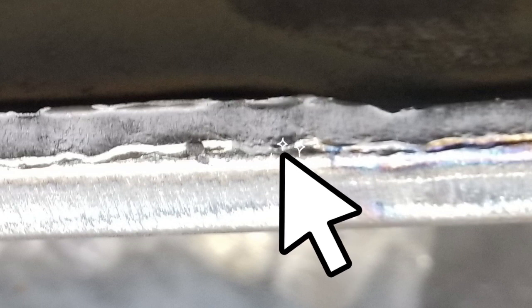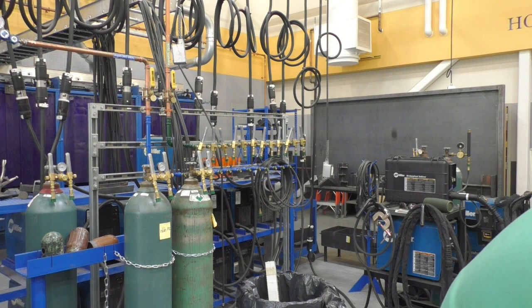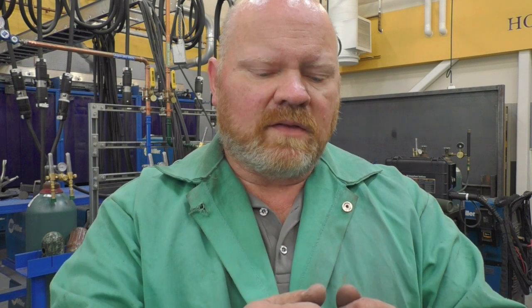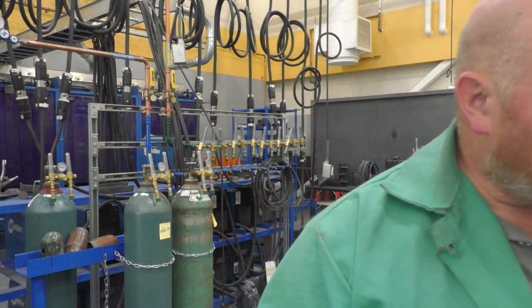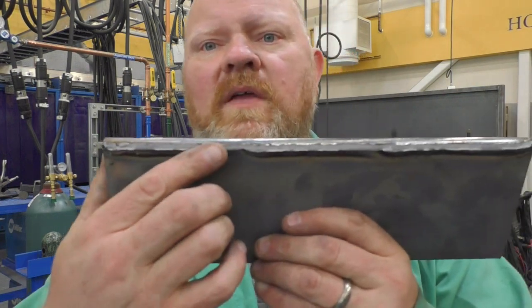There are areas where it appears to have missed it, right? And on those areas where it missed, you'd have to add up those physical lengths. Now, on a structural weld like this, you have to have root fusion, and you can have a maximum of 10% of that edge not fused. Again, that gets into the safety factor part of it. So on a 12-inch plate, you could have 1.2 inches of non-fusion maximum. The restarts look solid on this particular plate. I don't have any issues there, but the actual edge is a little bit questionable, okay?